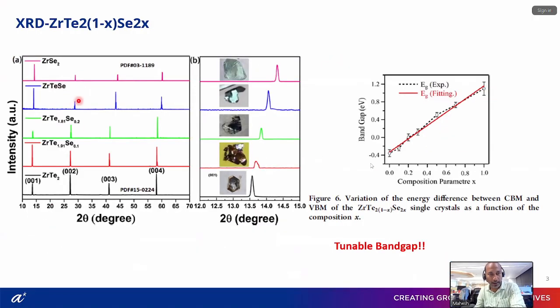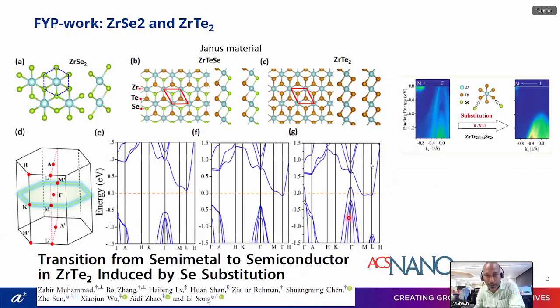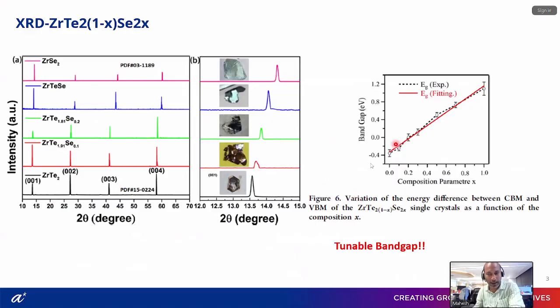Tellurium is bigger in size, so the lattice parameter increases, while the band gap decreases. This actually gives a negative band gap. Not negative exactly. It's this inversion that they count as negative, right? Yeah, they define it in some way. Like an order derivative, and if it's in one direction, then it has to be negative. Yeah. This is a nice